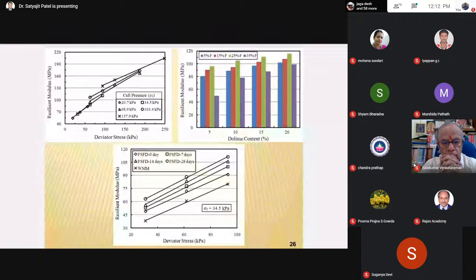That is FSFD, the fine steel slag flash dolomite mix, for 0 days, 7 days, 14 days, 28 days curing period. This MR value has also been compared with that of wet mix macadam, WMM. If you see, the bottommost line indicates the WMM, which is a very low value compared to the cemented base material. The MR value obtained for this steel slag flash dolomite mix, even for 0 day curing, is more than that of WMM, because WMM is an unbound material, so in the laboratory you will get very low strength or stiffness.